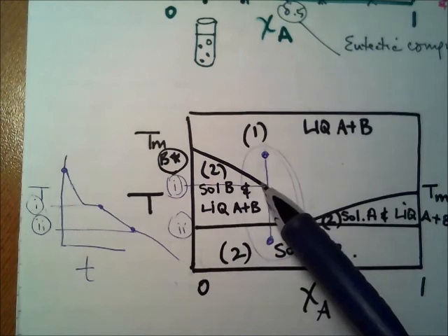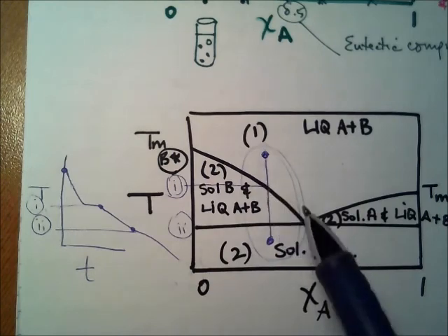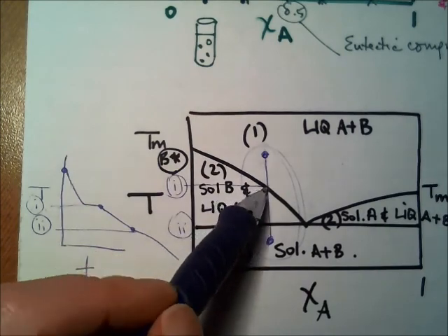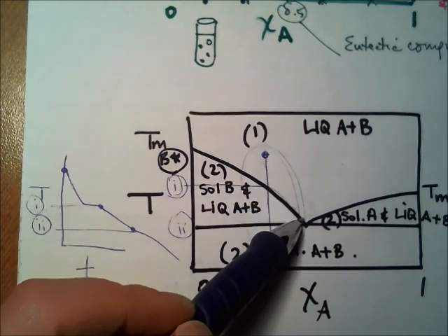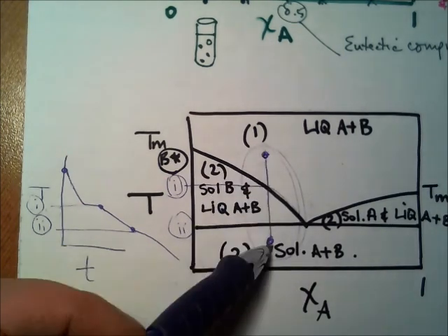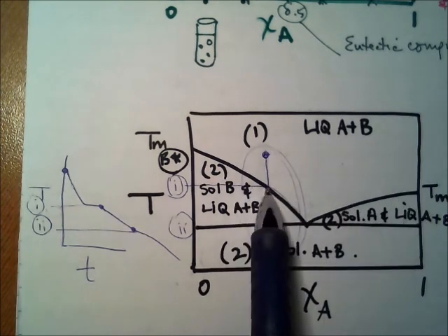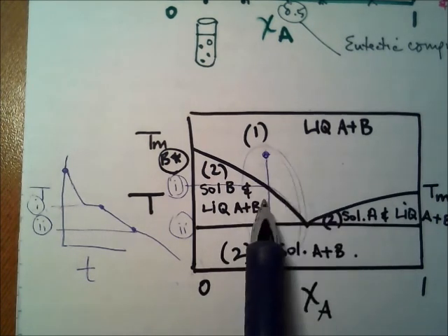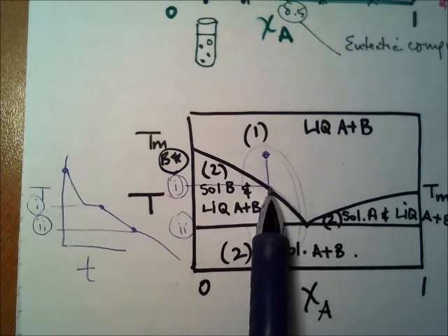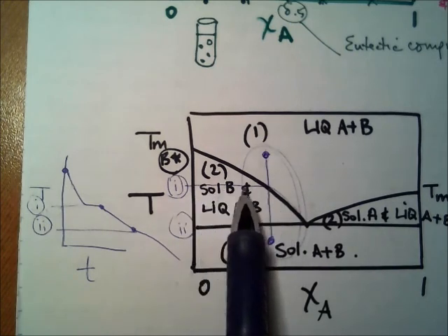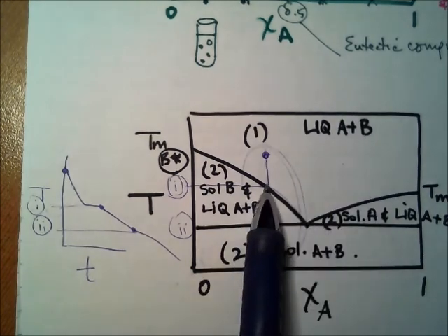It's freezing out of solution, so that as I cool more, yeah, you could slide down this, but we'll just look at this. So as I cool, what's it leaving behind? Well, it's leaving behind the tie line. I can't go anywhere with this tie line. It leaves me, I'm right here. Well, that's exactly what it's in equilibrium with. I have pure B and my liquid AB.